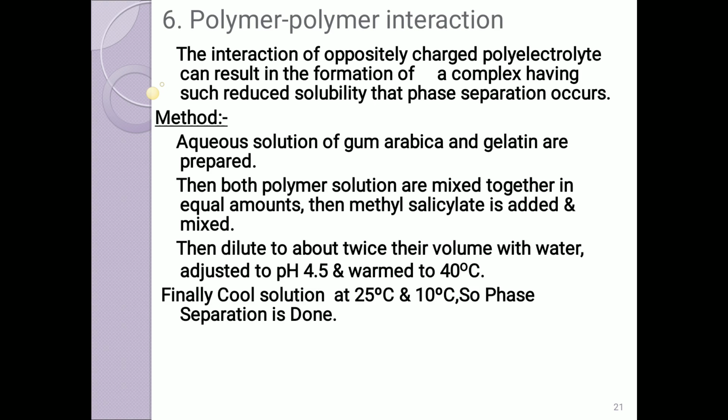The aqueous solutions of gum arabic and gelatin are prepared. Then both polymer solutions are mixed together in equal amounts. Then methyl salicylate is added. Methyl salicylate is our drug, right? We add methyl salicylate to that polymer.